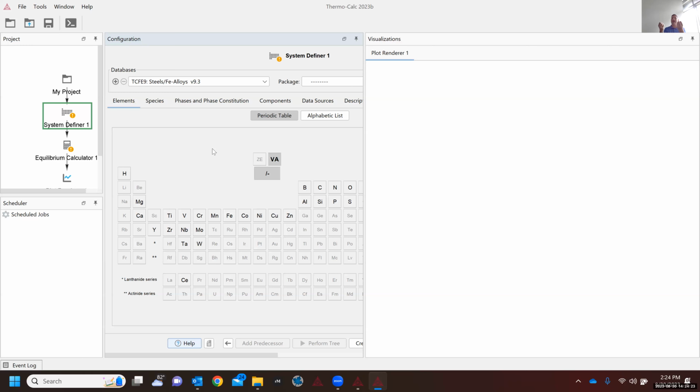Ternary systems, you tend to see a lot more discrepancy. But when you get to higher order systems, if you have well-described ternary systems, the last 100 years of thermodynamics and phase transformations research has shown that you really don't need much more beyond a ternary system. There are some quaternary intermetallic compounds, but they're very few and far between. The problem comes when you're trying to add a new element to an intermetallic phase. Maybe it's a ternary intermetallic phase, and you're trying to add a quaternary element, and that intermetallic phase doesn't exist anywhere where this fourth element is.